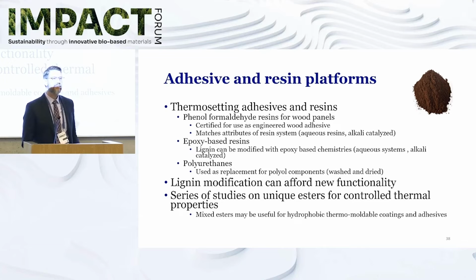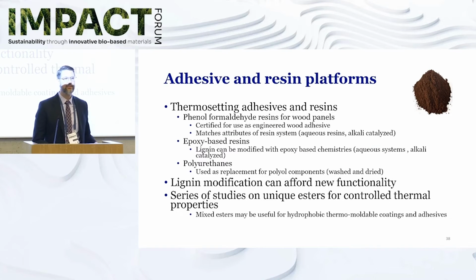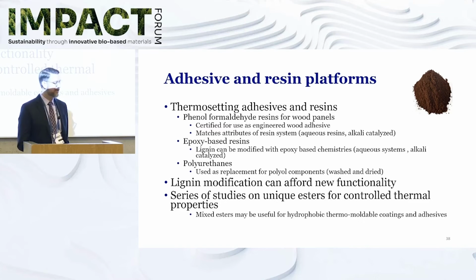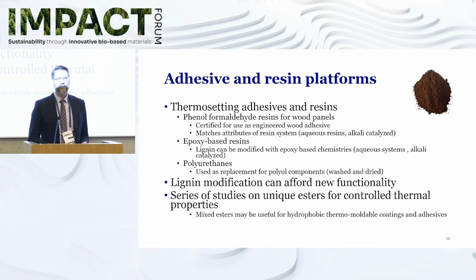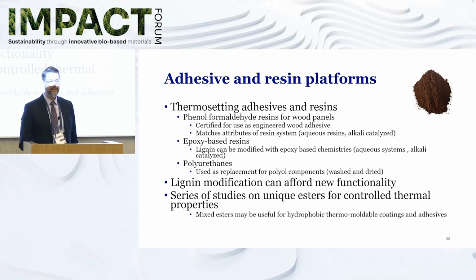Epoxy-based systems, the lignin's been used in these systems as well, and so again, if we want to epoxidize lignin, you can actually use aqueous systems with base catalysts, and so that's great because you don't have to dry the lignin. When you get it from the mill, you can just drop it in. If you wanted to use it in polyurethane foams, you usually have to dry the lignin and then mix it into that system, and so that's one issue there. Or you can dry the lignin and then do chemical modification of lignin, and so you can turn lignin into a thermoplastic, and then you can blend it with things like compostable plastics like PLA or PBAT, some of these common plastics out there. The issue there, though, if you don't do chemical modification, if you try to heat process kraft lignin, it almost smells like burnt hair. It has this nice garlic smell to it. So there's an issue there.